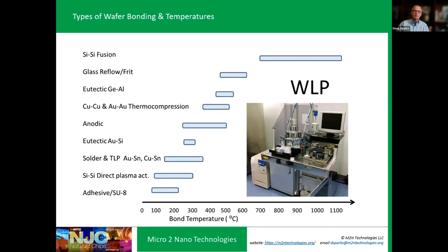Eutectic, germanium, aluminum, it's the same range. As you look at different alloys, eutectics, you may get down to 300. You can even get down with tin and indium alloys to under 200. But then you're worrying about, if you get the alloy bonding temperature low enough, you won't be able to do solder reflow at the board level. So you've got to think of these issues as well when you're lowering your bond temperatures.